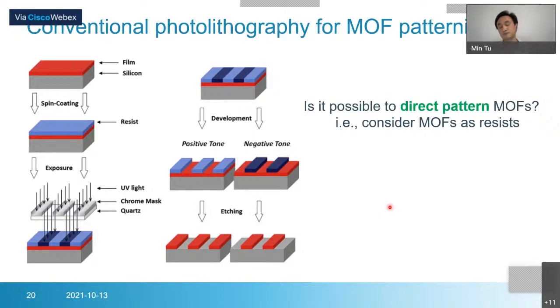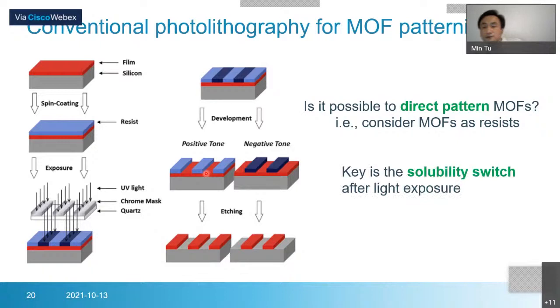So then I came up with an idea. Is it possible to directly pattern the MOFs? We consider the MOFs as a photoresist. Then after some light exposure, we can easily get the MOF patterning without any other resist. For using MOFs as a resist, the key is the solubility switch after light exposure. It means when we irradiate with light, it introduces some chemical changes in the MOFs, then a solubility switch, and then we can do the MOF patterning.